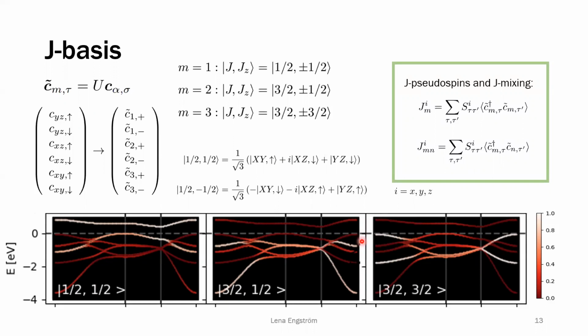So if we want to consider how these different states contribute to the magnetic order, what's reasonable is to look at order parameters that instead describe pseudospins in these J bases and how they contribute to the magnetic order. So for each of these three, we can have a different pseudospin magnetic moment. But since we want to look at this more generally, we also want to include some kind of order parameters that mix these two states. These don't physically mean too much in this perspective, but they do measure the discrepancy between just having a description of the individual bands and having a mix between different J states.